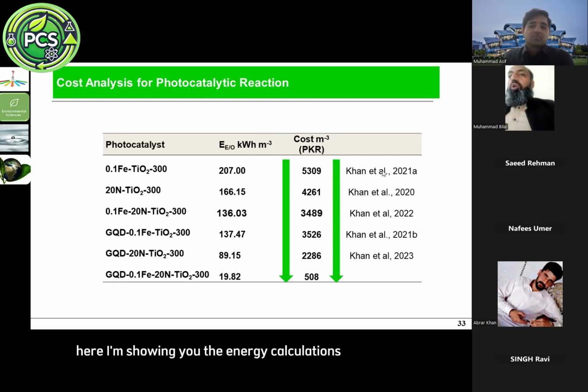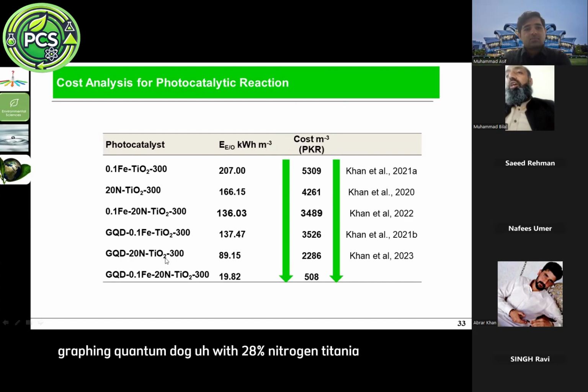Here I'm showing you the energy calculations, and we estimated the cost of the material, considering the temperature, considering the cost of the material, considering the time. So what we found here, our finest material, graphene quantum dot with 20% nitrogen titania. Material with iron, graphene quantum dot, iron, nitrogen, titania, that was showing almost lowest energy as well as lowest cost of the material, $508.